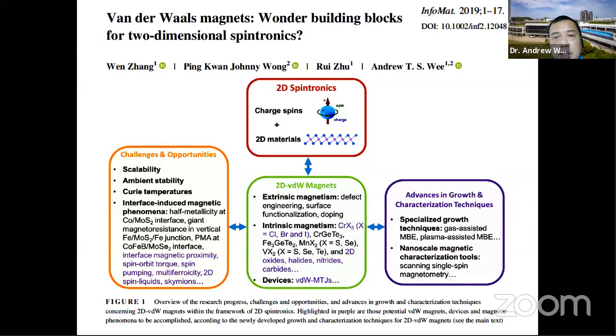So this is a summary chart that shows that in 2D spintronics, we utilize the charge and spin of the atoms in 2D materials. So you combine these two and you get 2D Van der Waals magnets. And these magnets could be extrinsically magnetic, which means the magnetism is from defects or functionalization or dopant atoms, or they could be intrinsic, which means they are magnetic without any modification in their pristine form. So for example, chromium germanium telluride, iron germanium telluride, manganese dichalcogenides, and so on. These have been shown to be magnetic. And of course, you can make a lot of Van der Waals devices from these materials.